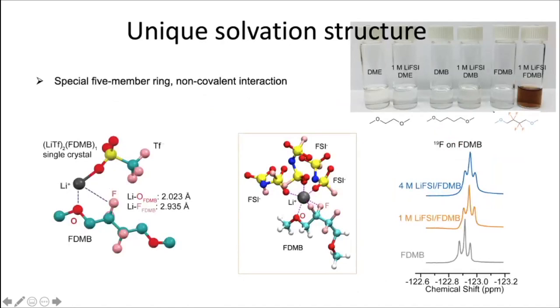based electrode? When we prepare these solutions using these three different solvents, immediately we can see there's a big difference when we use the FDMB with electron withdrawing fluoro groups substituted. You see a dark color here, and we were able to grow single crystals using lithium TF as the salt. Using the single crystal, we were able to see that in the new molecule, interestingly, the solvation of the lithium is through the chelation of oxygen and fluorine atoms instead of the typical two oxygens chelating to the lithium together. And this unique structure and the incorporation of the fluorine atom is responsible for the color change.